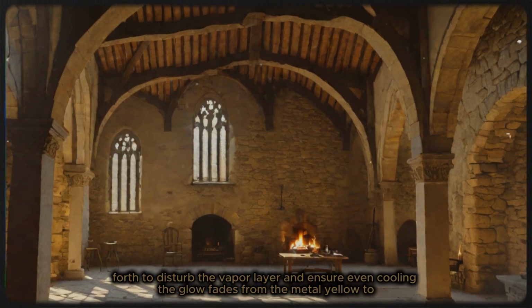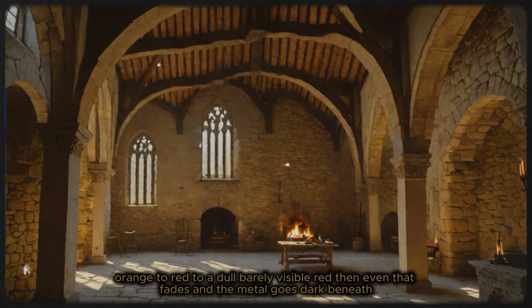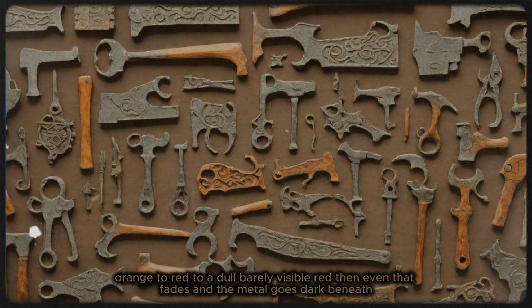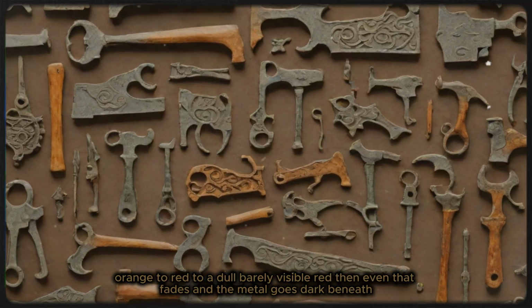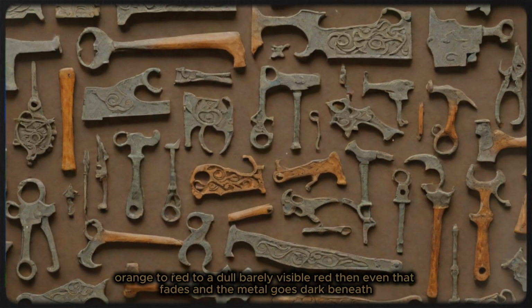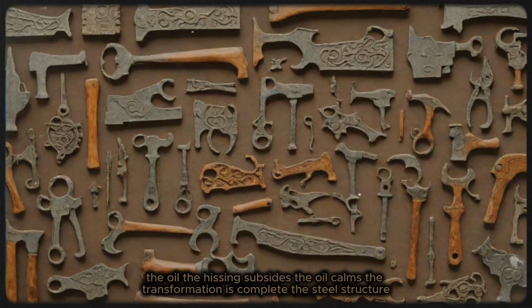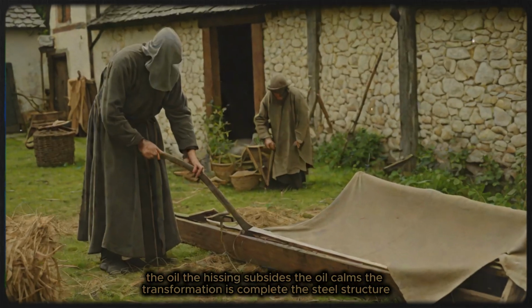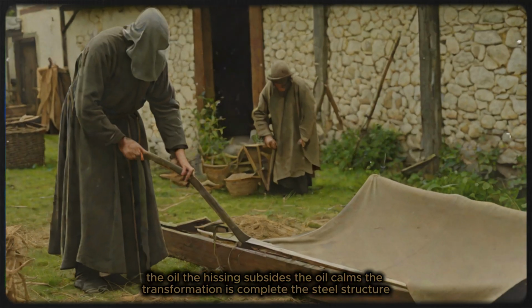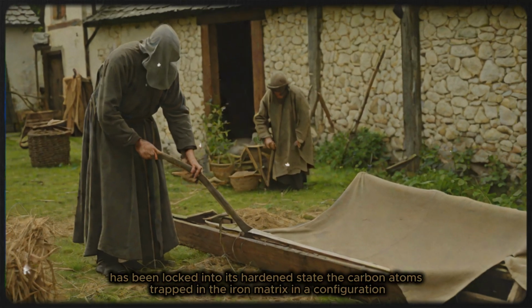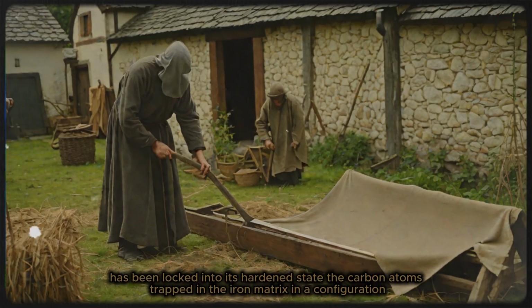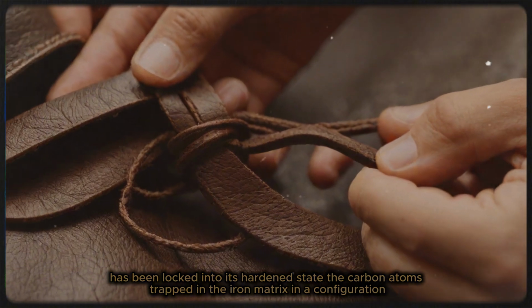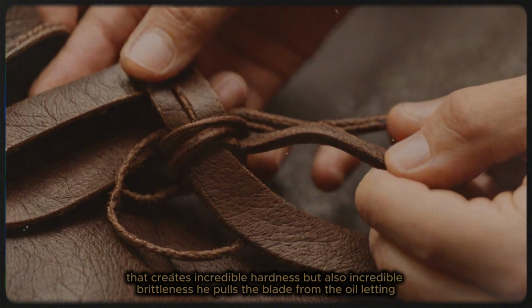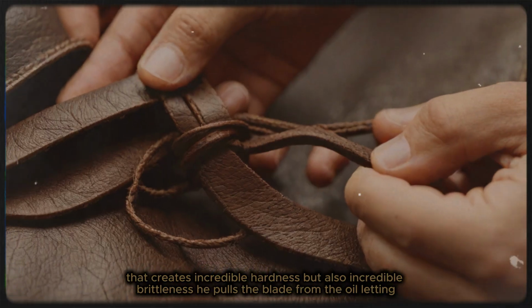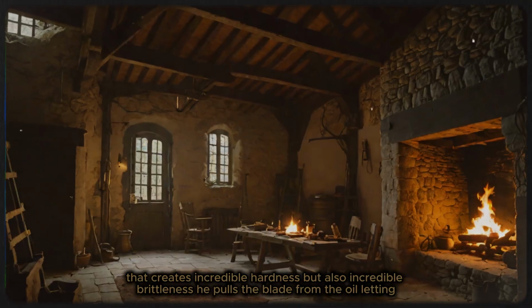The glow fades from the metal, yellow to orange to red to a dull, barely visible red. Then even that fades, and the metal goes dark beneath the oil. The hissing subsides. The oil calms. The transformation is complete. The steel's structure has been locked into its hardened state, the carbon atoms trapped in the iron matrix in a configuration that creates incredible hardness, but also incredible brittleness.